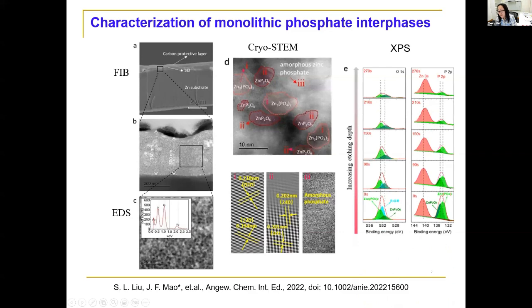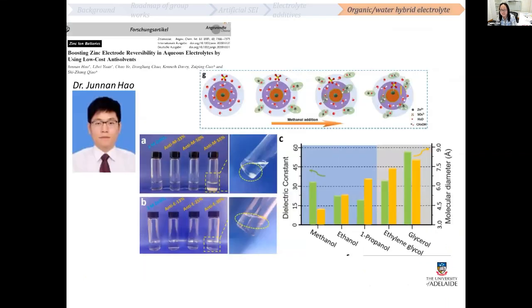From the XPS, she found that although with the aging time increase, the zinc peak increases and the phosphate peak decreases, the ratio between the different components, the zinc phosphate component, is still the same, indicating the uniformity and the monolithic feature of the SEI. So due to this very uniform and monolithic feature of the SEI, the battery using the DMNP water hybrid electrolyte exhibits very good performance.